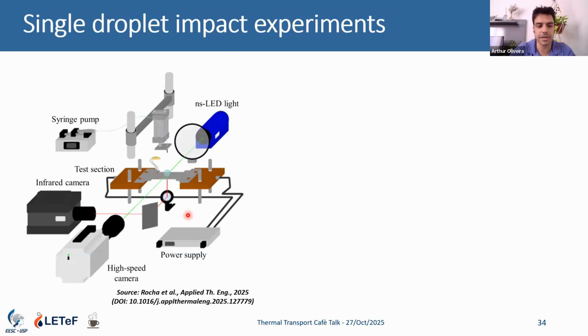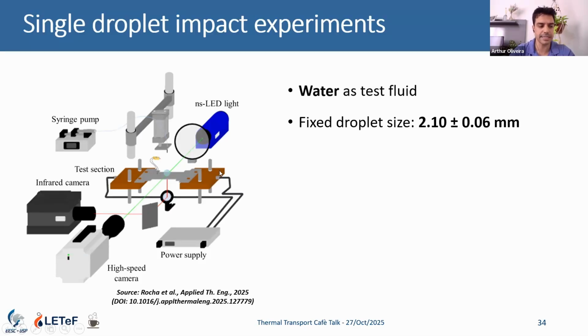So we have here the stainless steel plate, which is heated by Joule effect. We characterize the droplet impact by shadowgraph, and the infrared camera measures the surface temperature. And here are some characteristics of the tests.